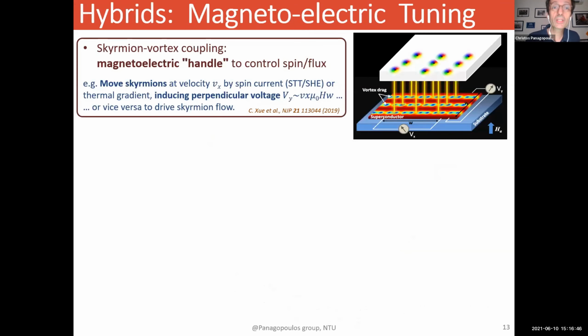But having such hybrids is also very useful for being able to have magnetoelectric tuning. So for instance, as you can see on the schematic on the right-hand side, if you have the superconducting vortices and the skyrmions being coupled, then this skyrmion-vortex coupling could become a magnetoelectric handle to control spin flux. For instance, you could use this to move skyrmions at a certain velocity by a spin current through spin transfer torque or spin Hall effect, or a thermal gradient inducing a perpendicular voltage, or vice versa to drive skyrmion flow, for example.